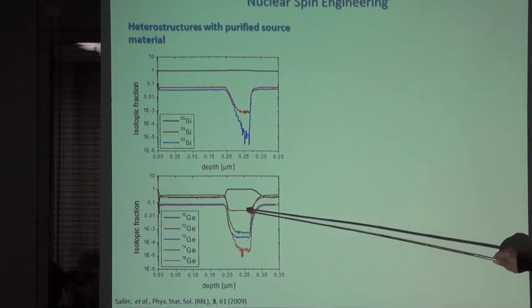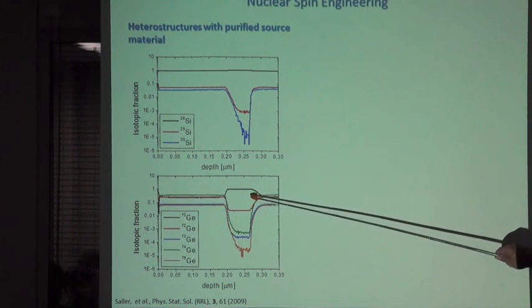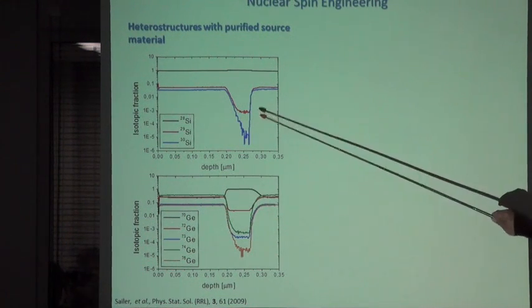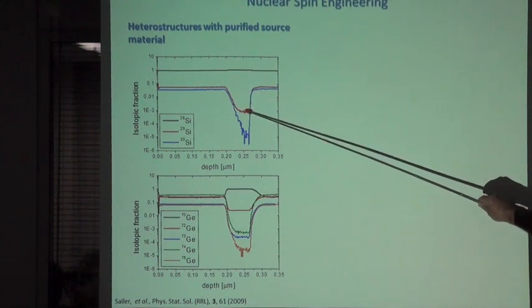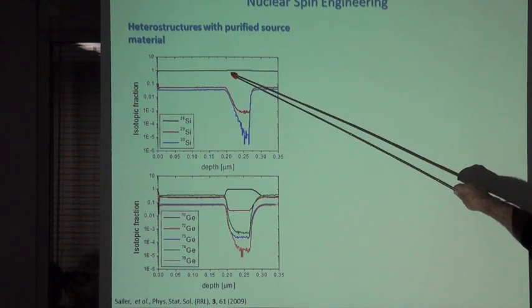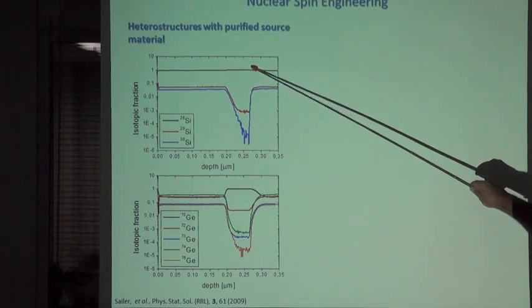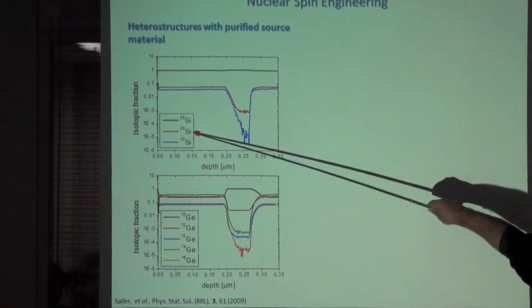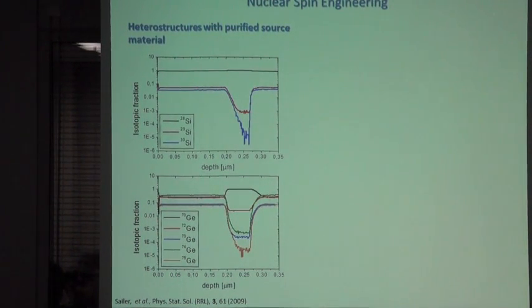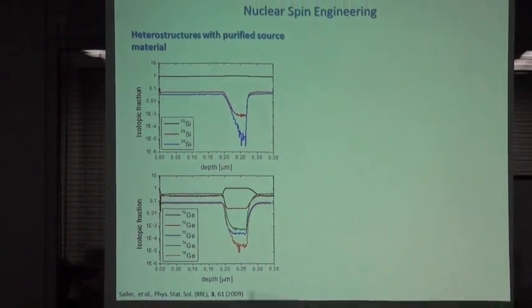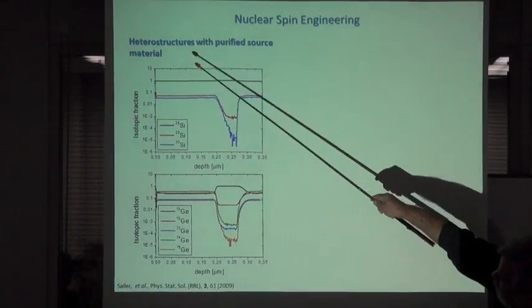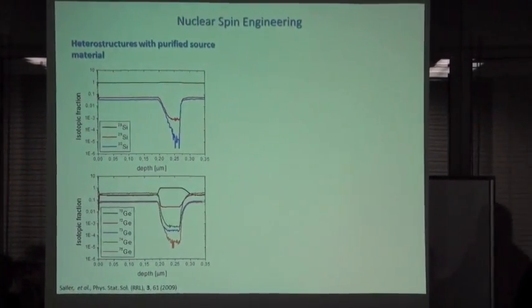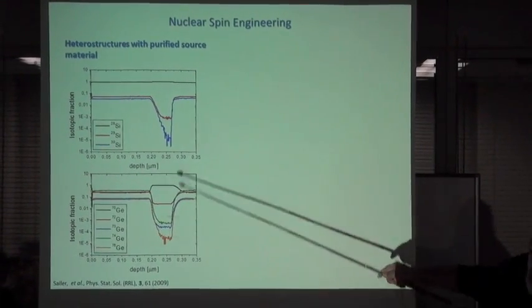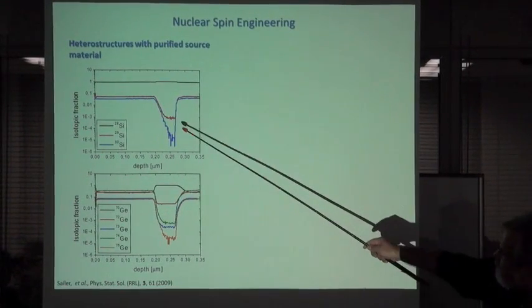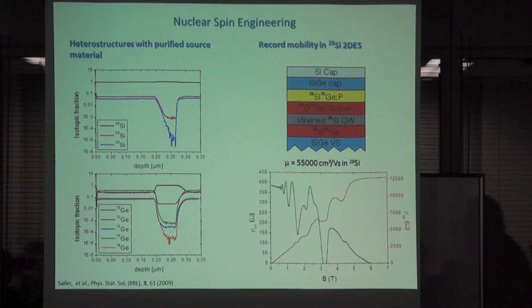And you see that we have here, this is a germanium. This is a silicon quantum well here. So here we have the silicon-28, a little higher, and reduction in silicon 29 and 30. And this is the kind of purity we get in such systems. So this is a logarithmic scale here, so it's a few orders of magnitude which we reduce, especially the silicon-29 is the important thing.